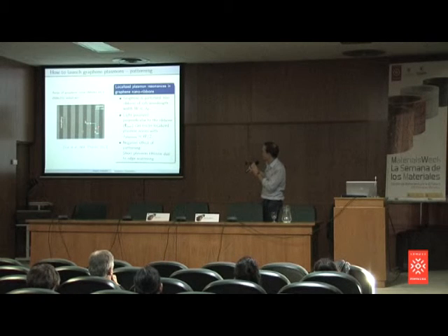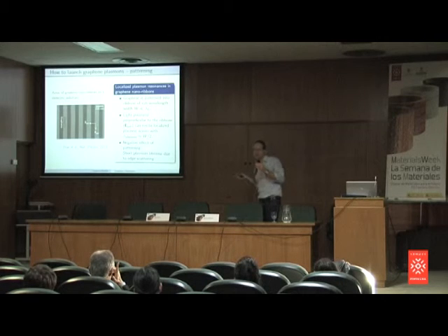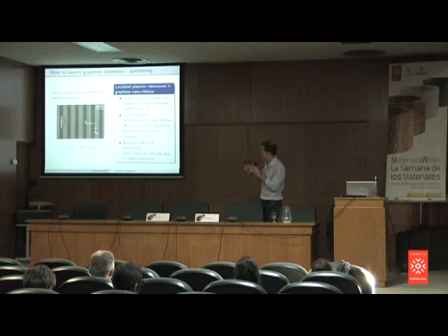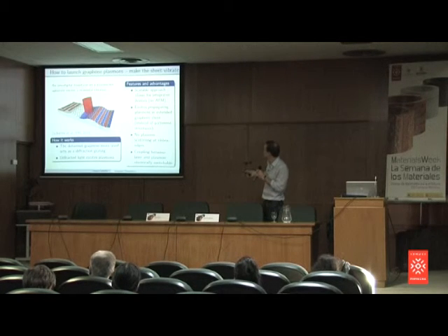And the problem with that is just that if you have to cut graphene, then the edges are usually not very clean. They are passivated or whatever, and if the electrons scatter there on this dirt, this has rather negative effects on the plasmon lifetime. So this is not for making long-lived plasmons. And this is where the idea of Jorge comes in, because Jorge told me that, well, we could as well make this structure in graphene without cutting it. And we came up with something like this.